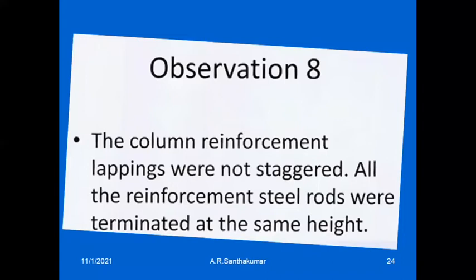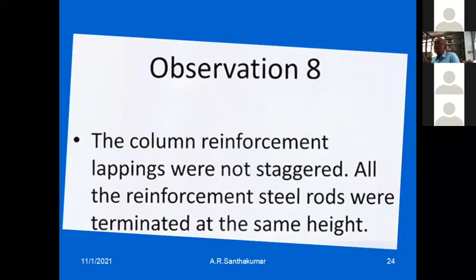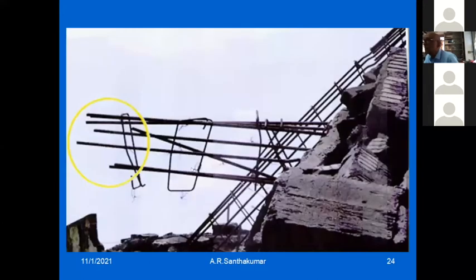Such staggering of lapping has not been done. And not only that, the lapping has been provided in the plastic hinge zone. Because the lapping had been provided in the plastic hinge zone, the bars pulled out and the bars did not yield. This is the column which has fallen down. You can see all the bars have been lapped at the same cross section and not staggered.